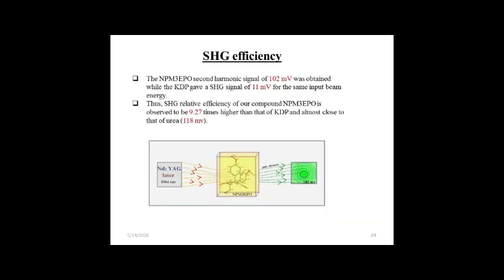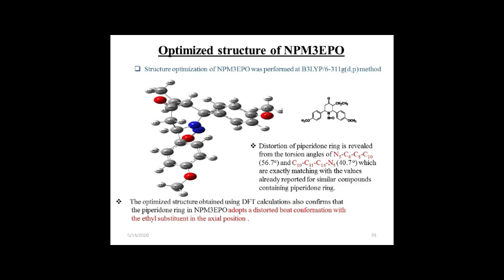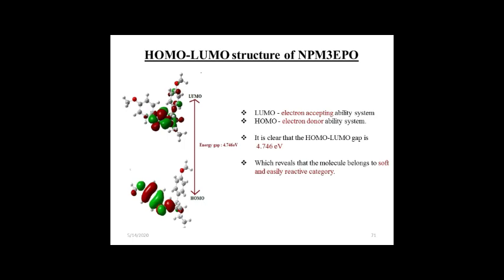Here the SHG efficiency is 9.2 times higher than that of KDP, almost close to urea at 118 millivolt. This is a good efficiency for our material. I am also involved in DFT studies. I prepared the density from the Gaussian software. We collect the structure, and by density functional theory, adopt the distorted boat conformation with the ethyl substituents at the axial position. This is the HOMO-LUMO structure of NPM3EPO.